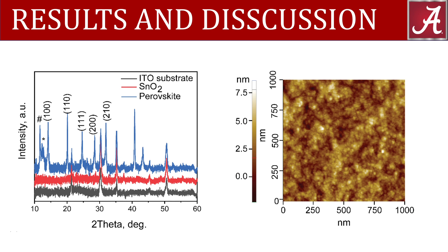The surface morphology of the tin oxide quantum dots was examined by atomic force microscopy. The AFM image shows well-dispersed tin oxide quantum dots with a relatively small quantum dot size distribution of around 3 nanometers. The films were found to be dense and pinhole free, with a root mean square surface roughness of 1.67 nanometers, which indicates that our deposition technique produced uniform, high quality, and smooth electron transport layers.